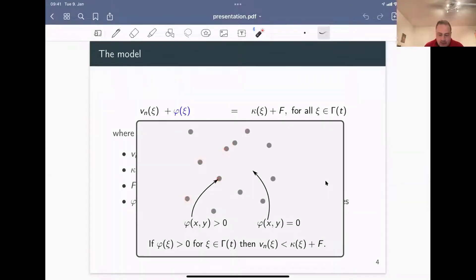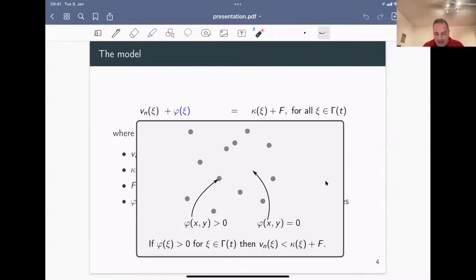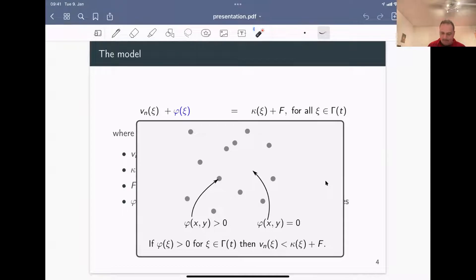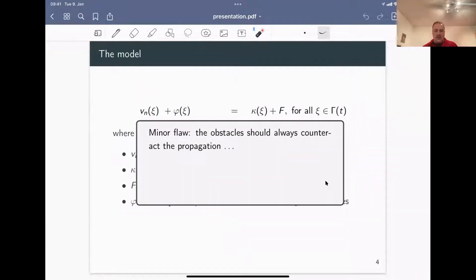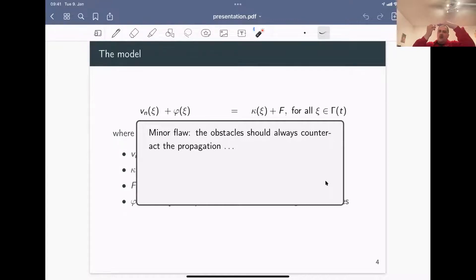Now let's add obstacles. Say the obstacles are randomly distributed in this plane. I model them by taking a function phi depending on position in the plane, which is positive inside those obstacles and zero everywhere else. Clearly, at a point in an obstacle I need some additional force to propagate through. However, this random function modeling obstacles has a directional problem - depending on which direction I go, the force is either positive or negative, which I'd like to avoid.